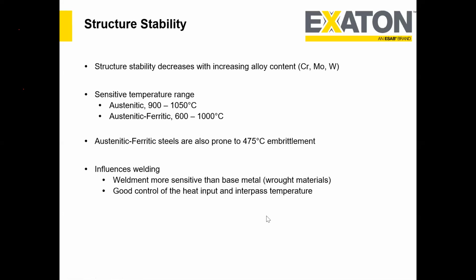So we need to control two very important parameters during welding: one is heat input and the second is the interpass temperature. These two are basically our golden rule or rule of thumb to get the desired microstructure, and the microstructure at the end of the day will give us the desired mechanical properties.